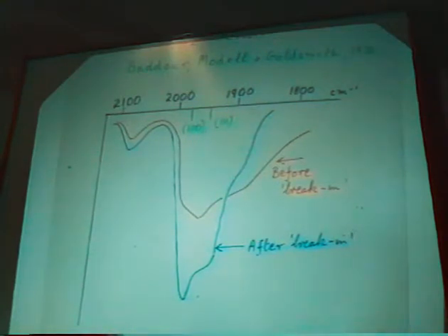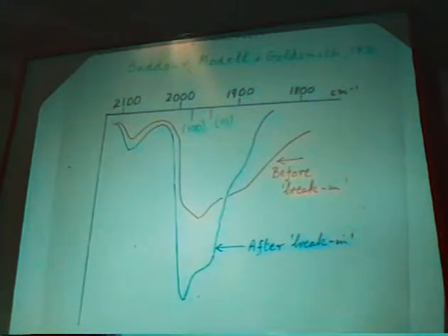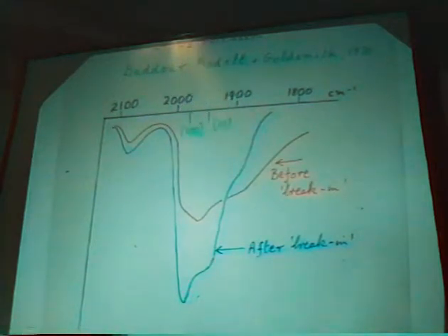There was a change in the catalyst, newly prepared, and after it had actually been used or broken in for the oxidation of carbon monoxide. This was the spectrum of the new catalyst, and you can see there are various sub-features corresponding to different species. But after the reaction had occurred at elevated temperatures, the spectrum had changed quite a bit in that the intensity had piled up at higher wave numbers. And what had clearly happened, among other things, was a change in the ratio of probably the 100 and the 111 facets on the catalyst.